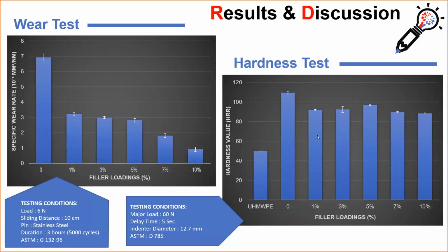For the hardness test, the result was expressed in Rockwell hardness value against increasing percentage of filler loading. The hardness test was carried out using 60 Newton major load, 5-second delay time, according to ASTM D785. The incorporation of ultra-high molecular weight PE filler into the epoxy seems to reduce the hardness, since the hardness of all filled composites is lower than the pristine epoxy.